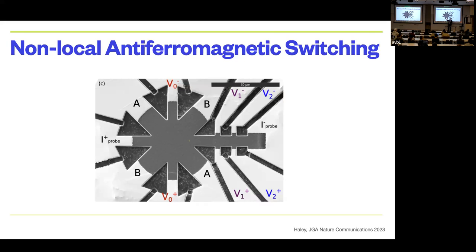Structurally stretching it, that's right. So if I'm stretching it here, but the whole system has to stay the same length, this part here has to shrink. And when it shrinks, the order parameter goes in the opposite direction. So that's one of the quasi-trivial reasons why we actually saw switching non-locally. In fact, what was interesting is that the signal here was much larger than the signal right here, the closer contact, and that's because it's closer to the edge of the system. So imagine stretching a rubber band. Anyway.